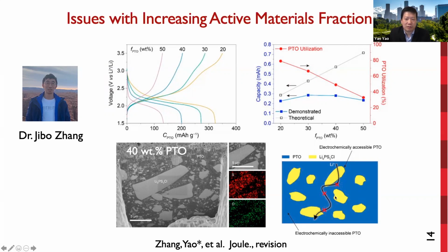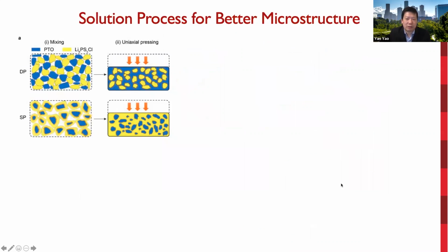So the reason for forming such undesired microstructure is related to the soft and compliant nature of organics. Organics deform easier before the lithium-ion solid electrolyte deforms. So to reverse this microstructure, we actually invented a solution process method that preforms core-shell structure particles, where the PTO core is surrounded by the electrolyte shell. So the deformation of PTO during the uniaxial pressing process could change the microstructure compared to the dry process.